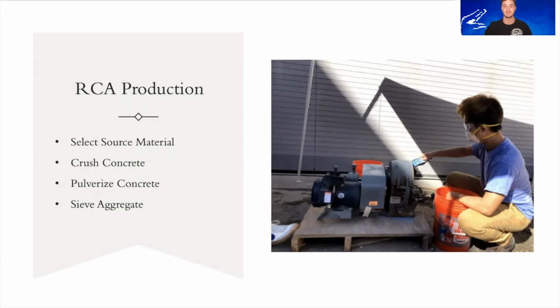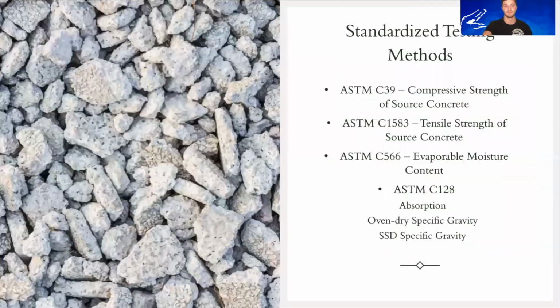After selecting the source material, the concrete is mechanically crushed and is then pulverized using a pulverizing machine in order to obtain small sizes of aggregate. After the RCA is pulverized, it is then put through a sieve shaker where aggregate sizes can be selected based on their size. Different sizes of aggregate produced from the sieve shaker can be used in mix design calculations.